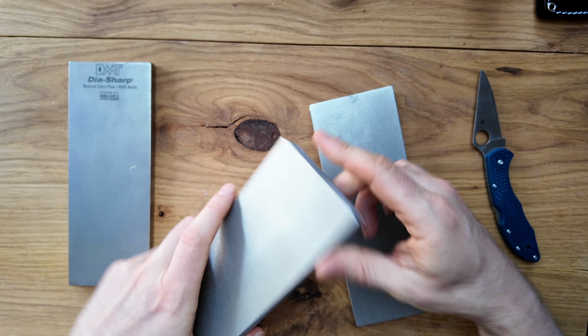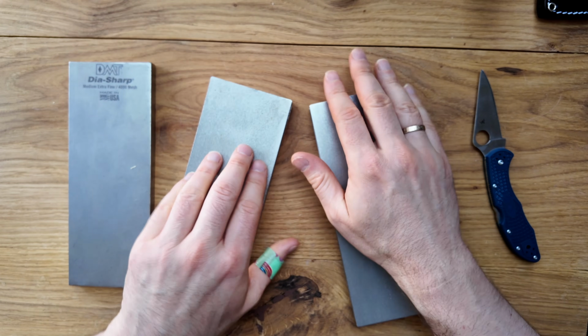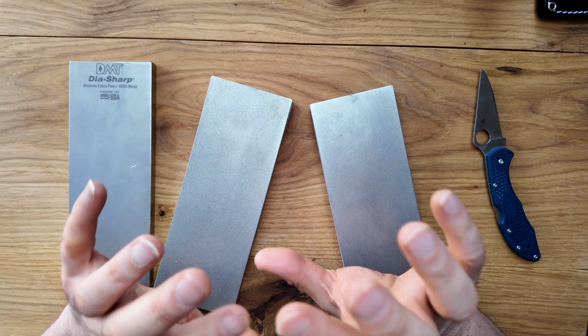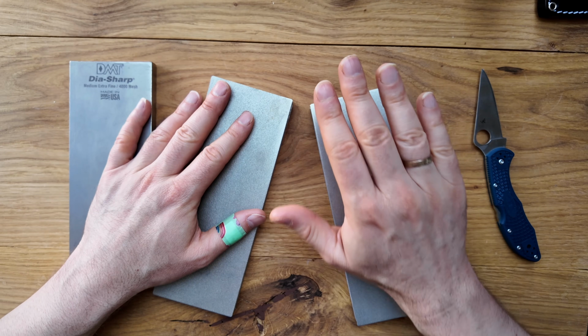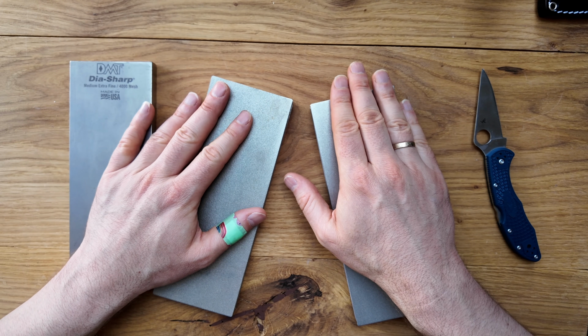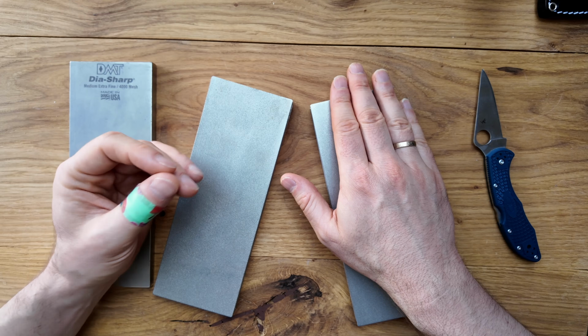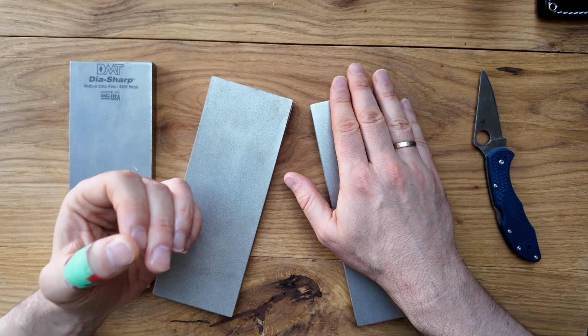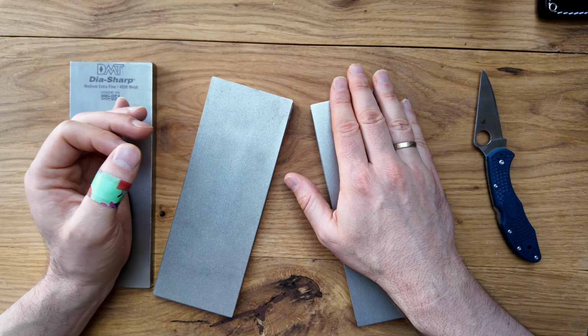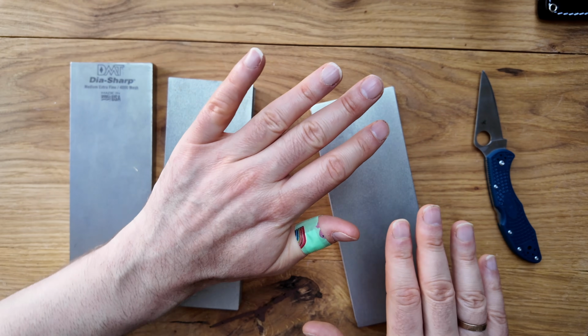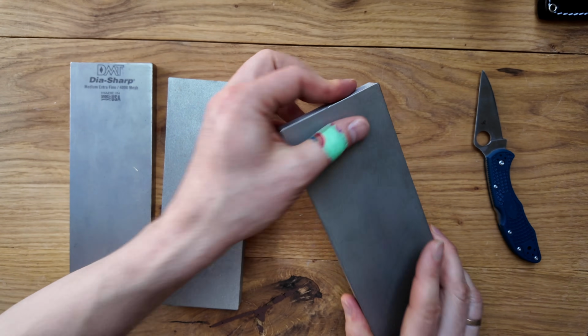These grain sizes correspond to roughly 150 grit and maybe even at best 180 grit. The stone is meaningfully coarser than advertised. That doesn't mean it's a bad stone, it cuts and it works, but it's not what the label says. Then we go to the 325 Sharpal stone.